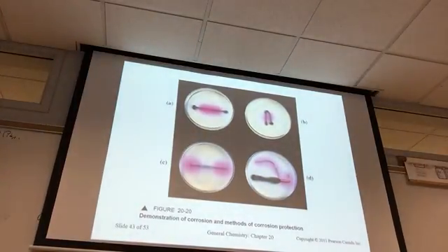And so as far as the iron goes, this is the cell that we can draw out. What is the anode? The anode of this cell is where the electrons are produced. The anode is where oxidation occurs. And so the iron here, which is the defective iron, is going to be the anode, because these are the irons that are going to be more easily attacked. And so we'll produce iron 2+ here, and then we're going to feed the electrons to the cathode. Well, the cathode is actually iron, and in fact they're both attached, but we have pristine iron. The pristine iron is harder to attack.